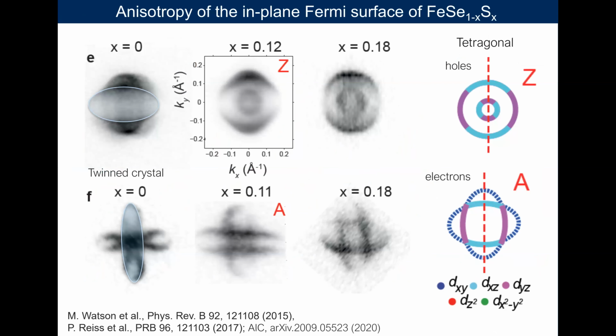So here are some data showing how the Fermi surfaces of a nematic system will look. This is a twin crystal, so you have to imagine the superposition of two nematic domains rotated by 90 degrees. We saw earlier that when we apply strain, we only see one particular domain. And when we change the sulfur concentration, the system becomes more and more isotropic, and obviously here it fulfills the four-fold rotation symmetry as expected from calculations.